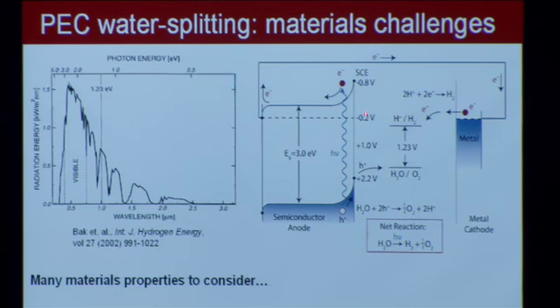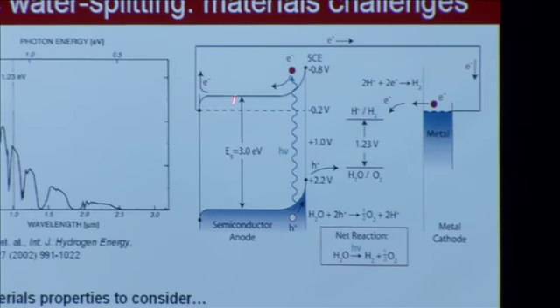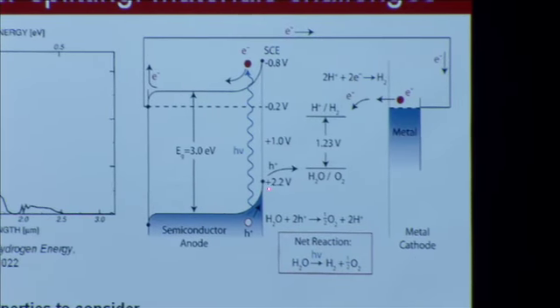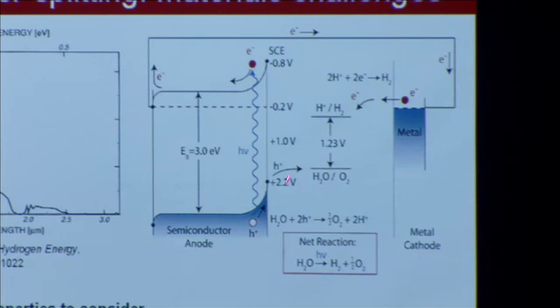Here's your semiconductor. We immerse a semiconductor inside of an aqueous electrolyte. And you can see this is the conduction band of the semiconductor. This is the valence band of the semiconductor. You form this junction right at that electrode-electrolyte interface. And that's actually a very important junction because that means when we shine light into the semiconductor, when we excite an electron from the valence band into the conduction band, we have an electric field right at that interface which is going to allow us to pull our electrons and holes apart so that we can actually do redox chemistry. We can do reduction on this side, and we can do oxidation down here.